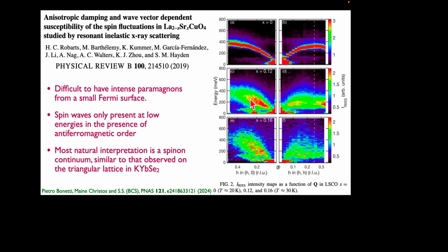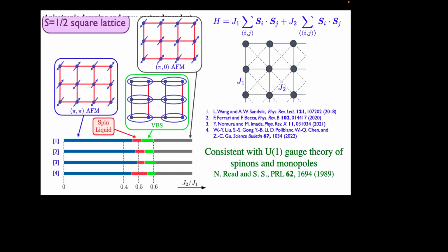But here we have to then ask about square lattice spin liquids. I told you about triangular lattice spin liquids, so what do you do on the square lattice? A huge effort over the last 30 years has been to take the square lattice Hamiltonian of spin-dot-spin interactions. This is the Hamiltonian that applies to the cuprates. And then you put in a second neighbor exchange J2, which is an exchange along the diagonals. Now in the real world, J2 is present, but it's rather small. But you keep cranking it up until you lose the Néel state that I told you about. The idea anyway is that maybe this will tell you something about the doped system. When you put in the mobile electrons, how do you lose this magnetic order and get a spin liquid state?